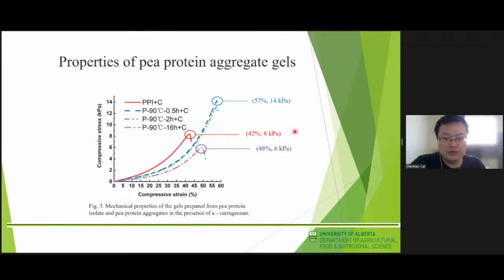Based on our previous research, no gels were formed from untreated pea protein isolate solution or pea protein aggregates alone by heating at 95 degrees at neutral pH, because the protein concentration of 7.5% applied in this research was lower than the minimum gelling concentration of pea proteins. Our research work demonstrated that pea protein could form a gel at a protein concentration of 15% or higher when heated at 95 degrees for half an hour.